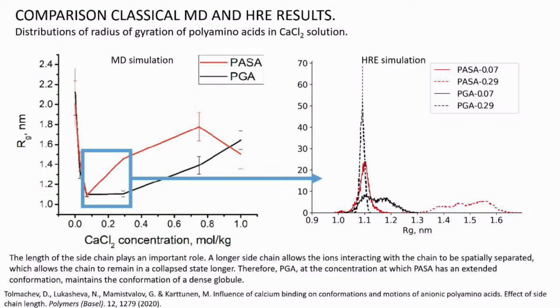You can see that at higher concentrations of salt, the polyglutamic acid is collapsed while aspartic acid is elongated and the distribution of this chain is much wider. The reason for such behavior, we believe, lies in the length of the chain, because it's the only chemical difference in our polyamino acids. The idea is that calcium ions adsorbed on carboxyl groups interact with each other and push away a little bit from each other. And to maximize the number of adsorbed ions, the chain has to be elongated.